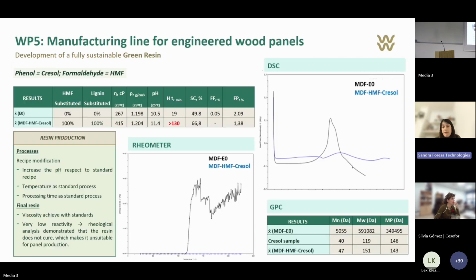In the case of developing a green resin with cresol and HMF, we only modified the pH starting in the standard recipe. The rest of the parameters, such as temperature, were not modified. Despite obtaining the final resin, the gel time was high enough to say that this resin doesn't cure, has no reactivity.